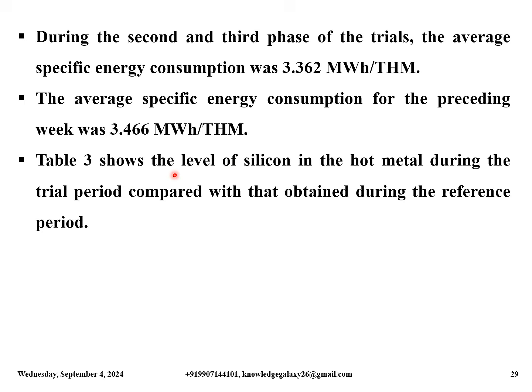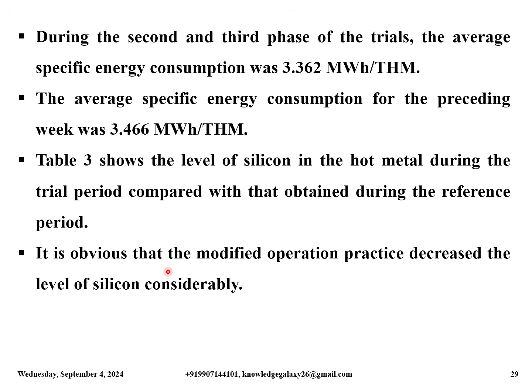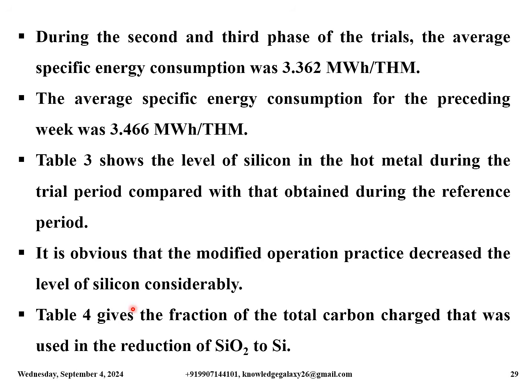Table 3 shows the level of silicon in the hot metal during the trial period compared with that obtained during the reference period. The table is shown in the next slide. It is obvious that the modified operation practice decreased the level of silicon considerably. And table 4 gives the fraction of the total carbon charge that was used in the reduction of SiO2 to Si.